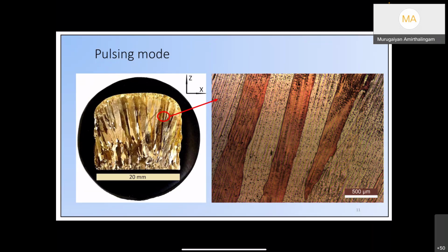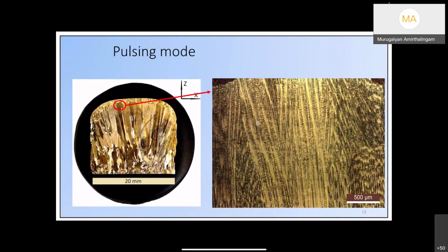So when we don't control anything, we just deposit in conventional pulsed gas metal arc welding. You see that. This is what we call a columnar microstructure, a directionally solidified dendritic microstructure. It's like if you take any simple plywood, you see wood fibers oriented in one direction. That's what we call an anisotropic microstructure, isn't it? And the properties would be different if you apply a load along this direction versus perpendicular to the fiber direction.